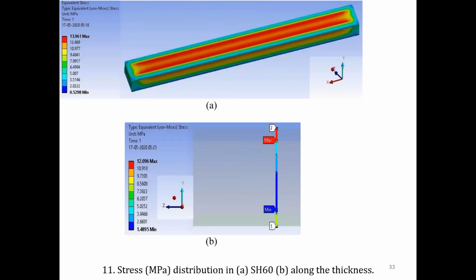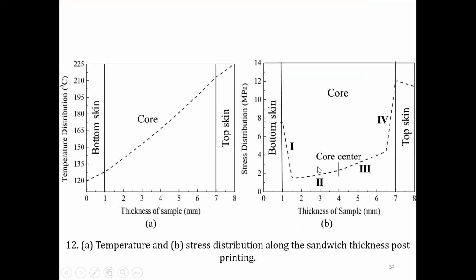Now, the temperature and stress distribution along the thickness of the sandwich, you can see in B. And we can clearly observe the temperature distribution through the thickness of SH60 or for that matter any sandwich. So temperature increases from the bottom to top through the foam core. The bottom and top skins' proximity to the bed and nozzle, the bed being maintained constant at 120 degrees C, and the nozzle at a very elevated temperature of 225 degrees C, are naturally seen in this distribution.